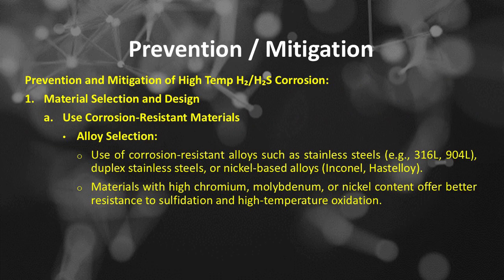Below is a detailed explanation of prevention and mitigation methods for high-temperature hydrogen (H2) and hydrogen sulfide (H₂S) corrosion. Number 1 is material selection and design. A: use corrosion-resistant materials. The first is alloy selection: use of corrosion-resistant alloys such as stainless steels, e.g., 316L, 904L, duplex stainless steels, or nickel-based alloys, Inconel, Hastelloy. Materials with high chromium, molybdenum, or nickel content offer better resistance to sulfidation and high-temperature oxidation.